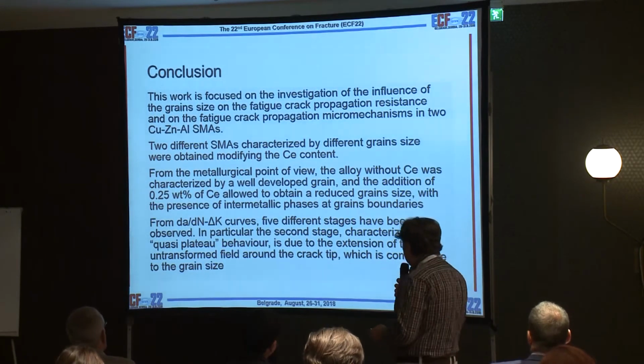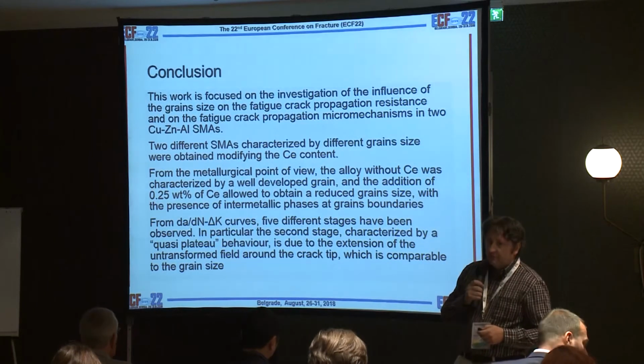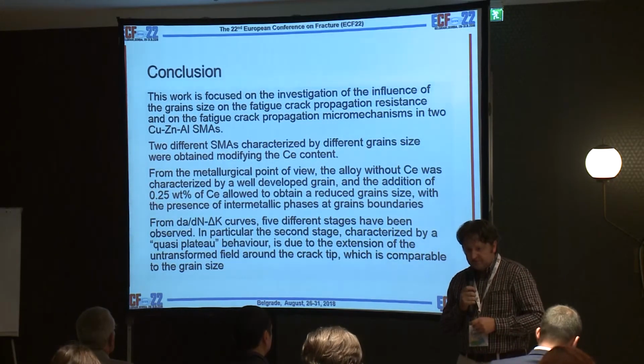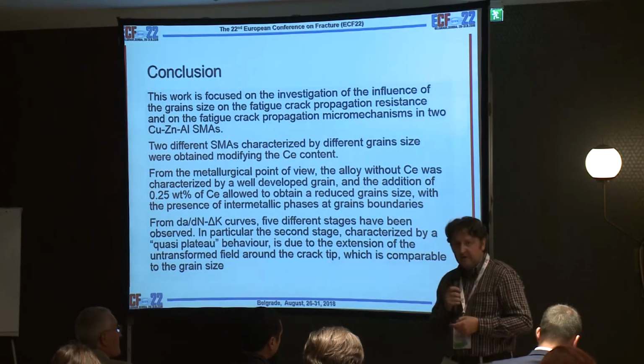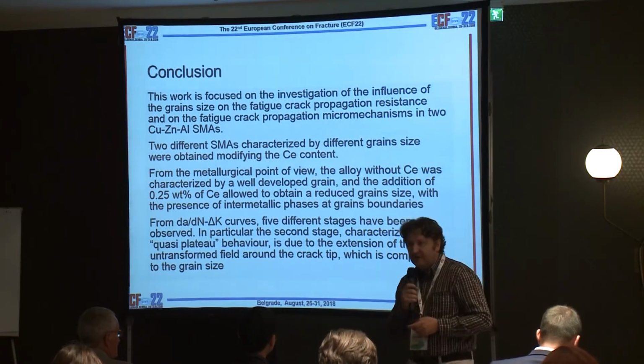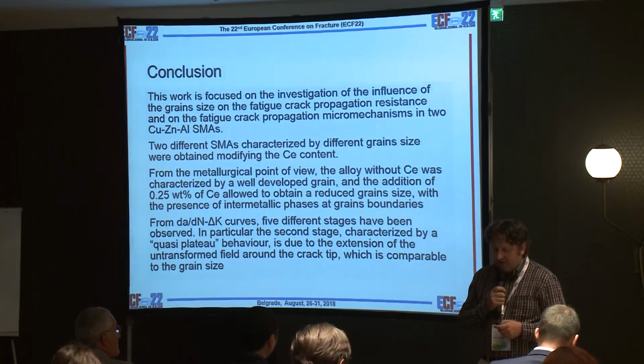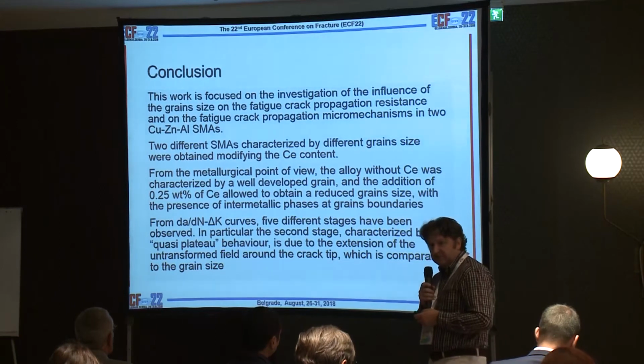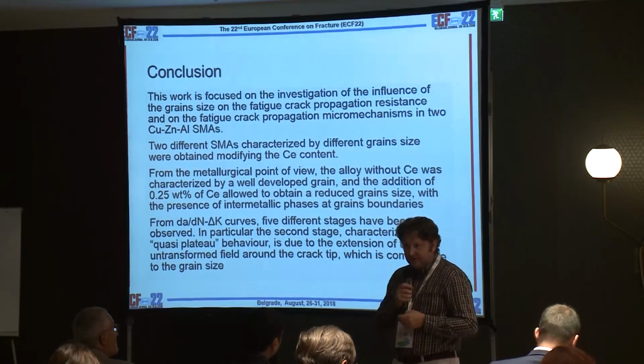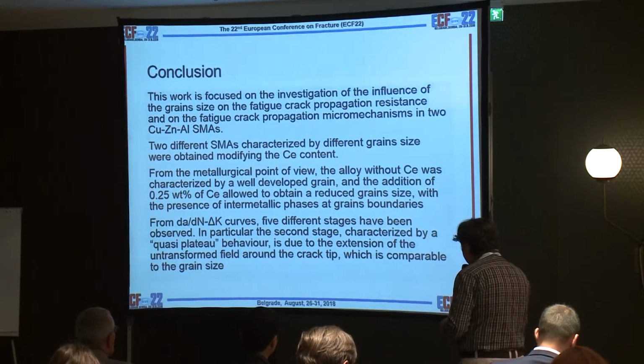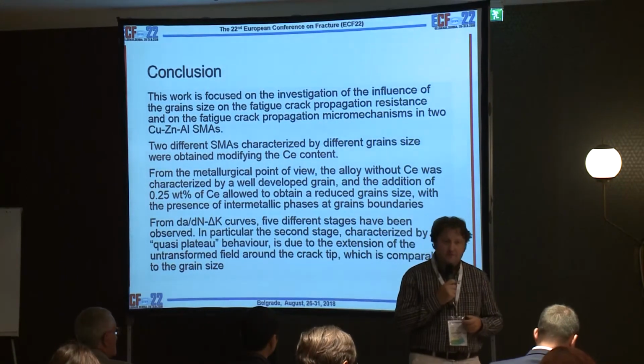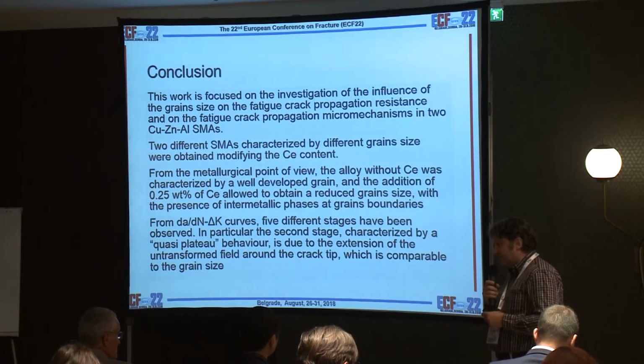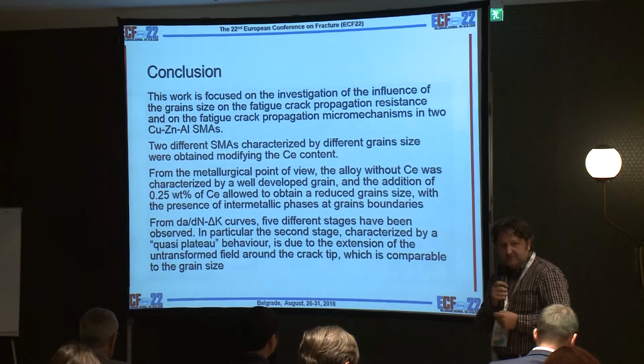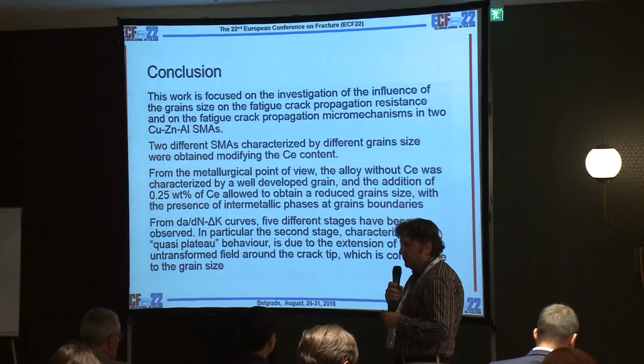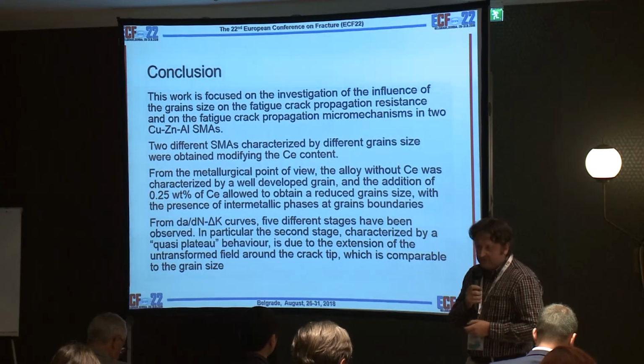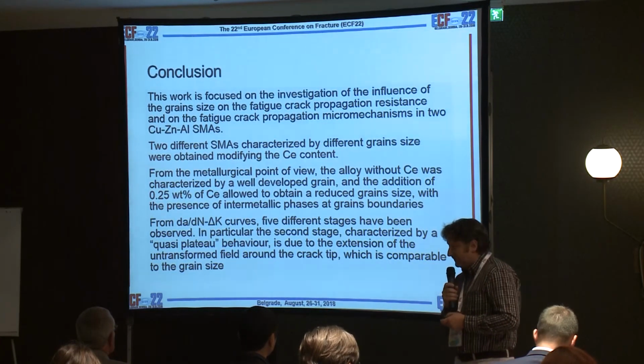So here I summarized the conclusions. We have 2 main conclusions. The first conclusion is in terms of the metallurgical influence of cerium on the grain size of copper-based shape memory alloy. The addition of cerium strongly reduces the grain size and strongly influences the mechanical behavior of this alloy. And the second one is the influence of the change of structure in terms of fatigue crack propagation, which in this kind of material seems to be characterized by over 3 stages, the stages usually observed in traditional metallic alloys. Thank you very much.